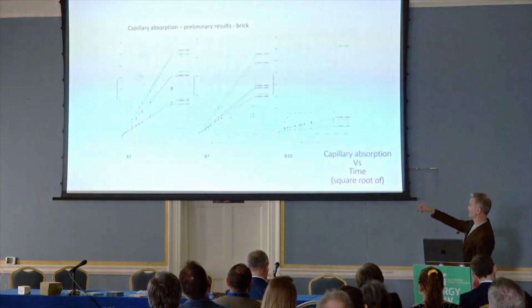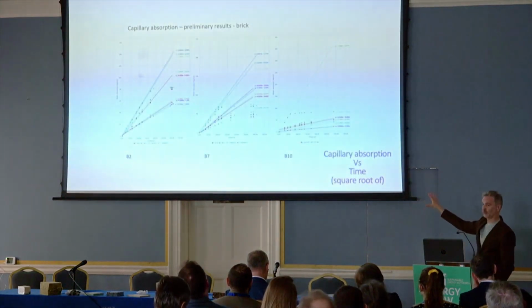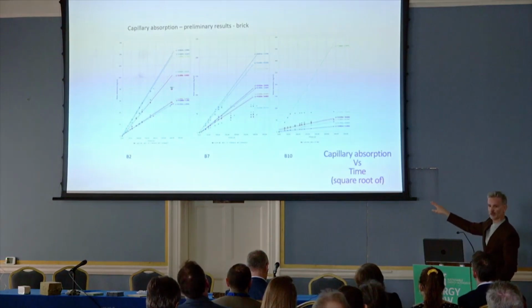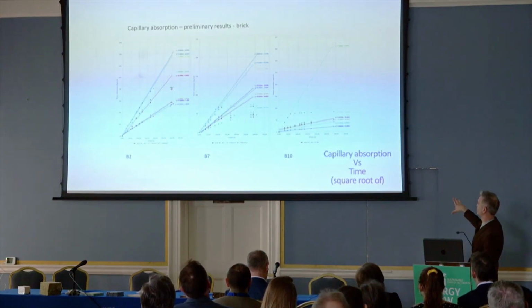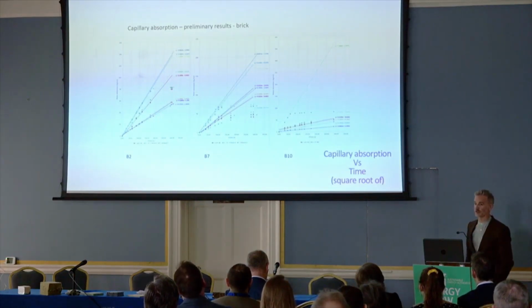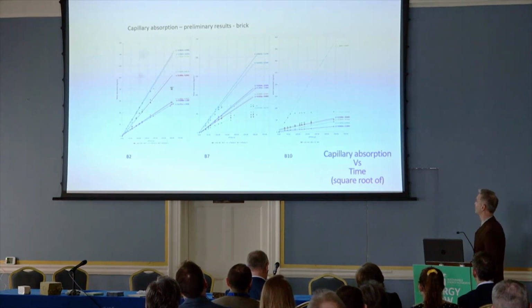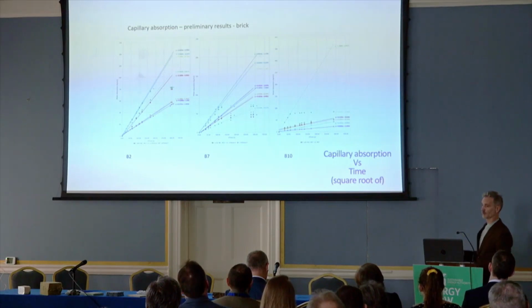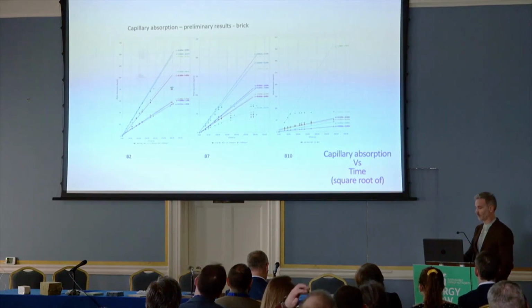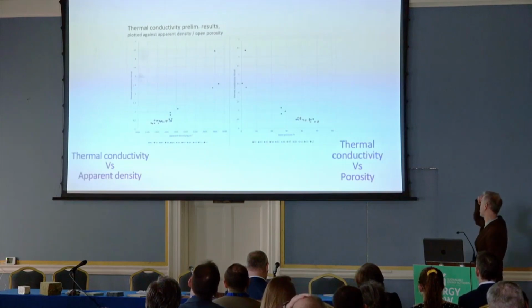And as a result, these are B2, B7, B10, three different types of bricks. I think they're primarily yellow bricks. And what we see is a wide variability across those samples as a result. These are results for capillary absorption against time. So a much greater uptake of moisture as a result of the different capillary absorption parameters.